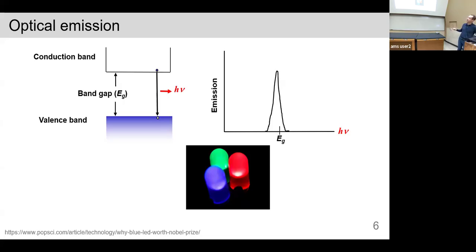So this is plotting how many photons you get out versus photon energy. And it's pretty close to the band gap. So that's another way to estimate this band gap property. And it's the basis for light-emitting diodes. You electrically inject an electron into the conduction band and a hole in the valence band. And this process results in whatever color light you want, which depends on the band gap. So you can tune the color.